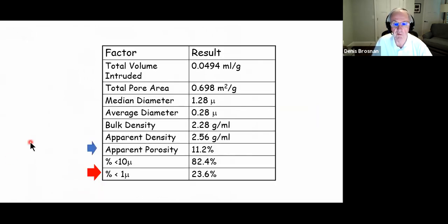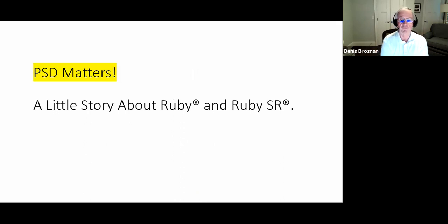We get a certain data output from our mercury porosimetry test. It gives us bulk density and apparent density values, but I just wanted to highlight the apparent porosity in this product was 11.2%. That's the amount of void space within the ceramic. But then we can characterize the pore sizes. Less than 10 microns, we had 82%, less than 1 micron, about 23%. So there's a big band of pores in this 1 to 10 micron area, and you saw it on the previous graph. Just go back and look at it if you want to, and you can see that. So pore sizes make a difference.